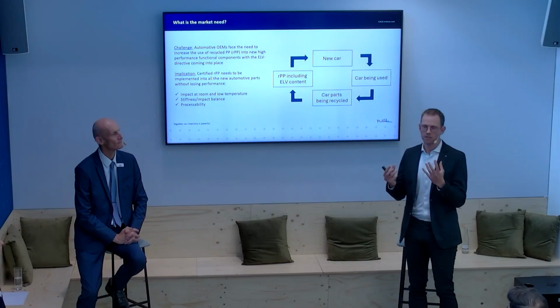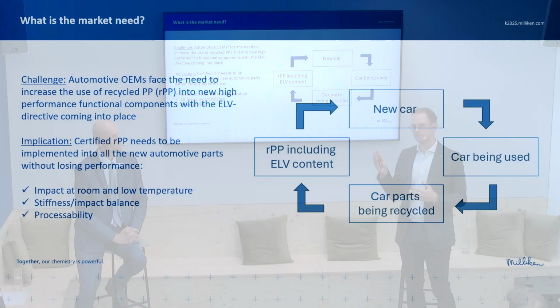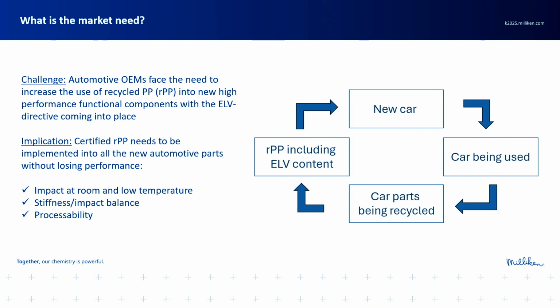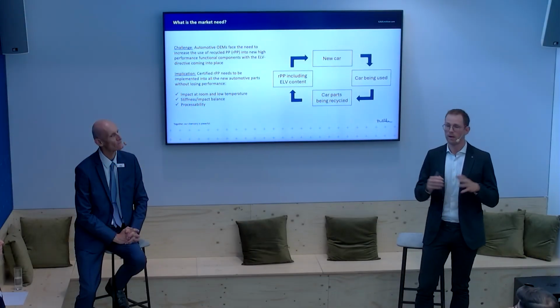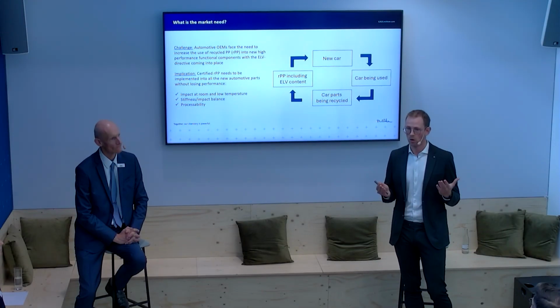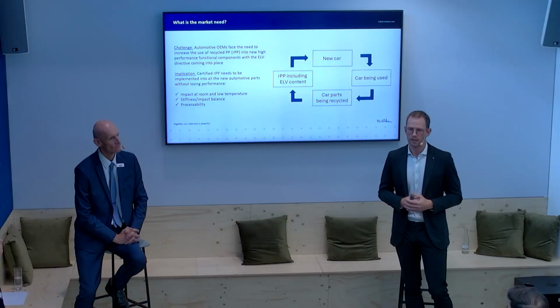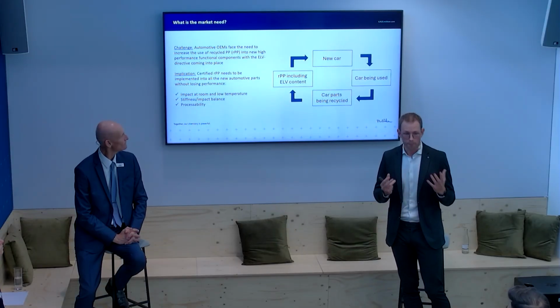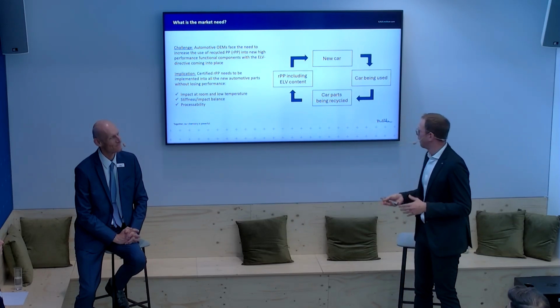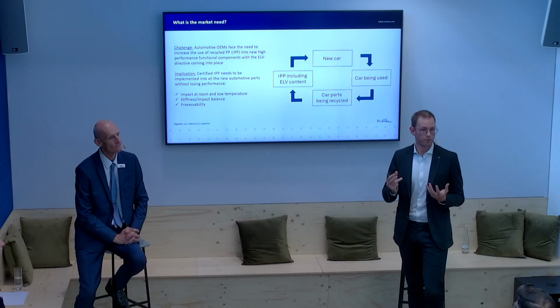The idea is you buy a car, you consume it over a couple of years, then these car parts are being recycled and reintegrated into the stream. So the idea of this ELV regulation is that by 2032, car parts, on average, need to contain 20% of recycled material. Out of this 20%, 15% needs to come from end-of-life vehicle. So when you think of an example, it can be bumper to bumper or door panel to door panel, depending on the mechanical technical needs that you have. But there is always a but. The idea is here that we still have the very high mechanical performance that the auto industry has. Think about processability, that is directly linked to melt flow rate. Think about impact performance, that is in this case notched impact performance at room temperature, but also at minus temperature.